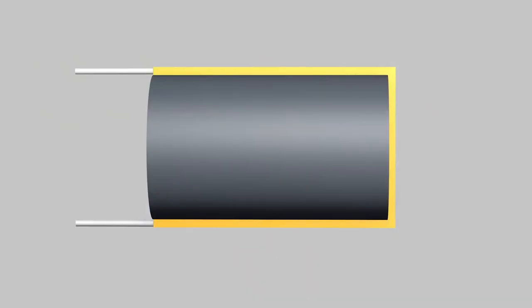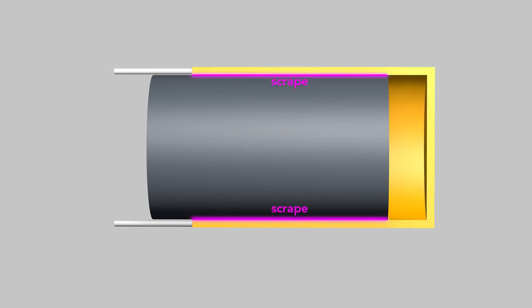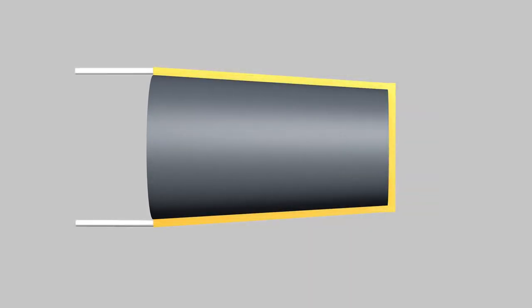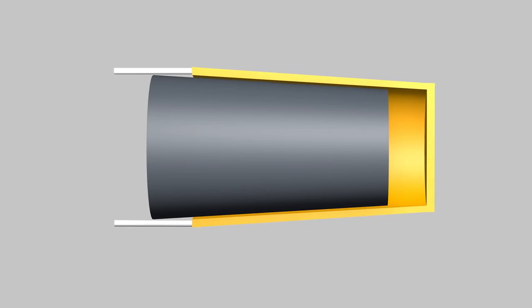Another very important aspect of mold design is the draft angle. If a part has walls that are exactly 90 degrees, it will be very difficult to eject because its inner walls will scrape the core half of the mold. Also, the vacuum will be difficult to break because air cannot readily enter. However, if the walls are slightly tapered, even just one or two degrees, it becomes much easier for the part to be removed, because once the part moves slightly, the walls are no longer in contact with the core half and air can rush in.